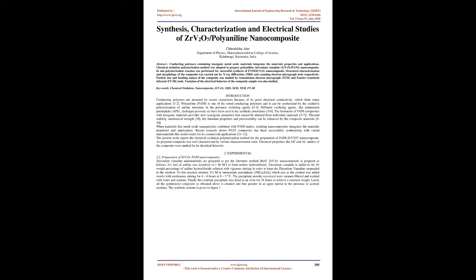Structural characterization and morphology of the composite was carried out by X-ray diffraction, XRD, and scanning electron micrograph tools respectively. Particle size and bonding nature of the composite was studied by transmission electron micrograph, TEM, and Fourier transform infrared, FTIR, tools. Variation of the electrical behavior of the composite sample was also studied. Keywords: chemical oxidation, nanocomposite, ZrV2O7, XRD, SEM, TEM, FTIR.